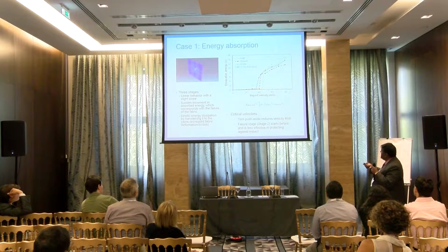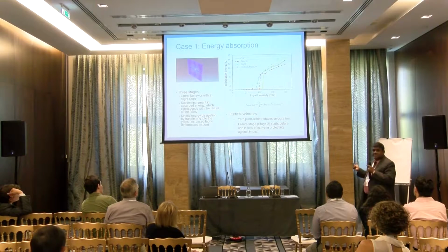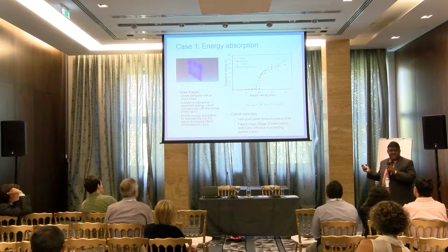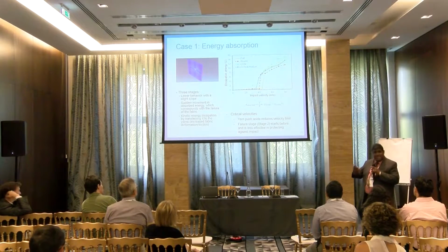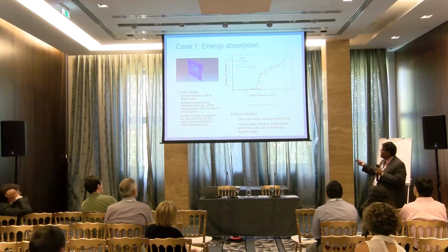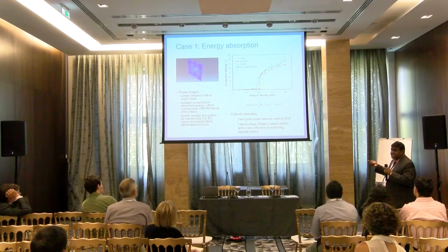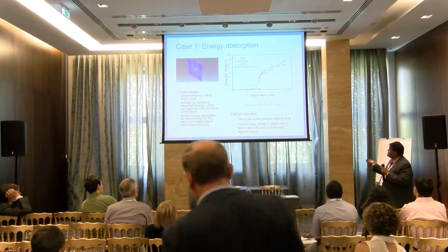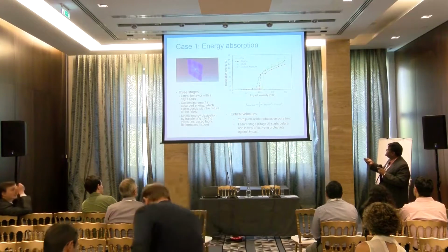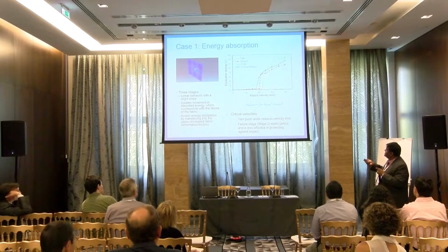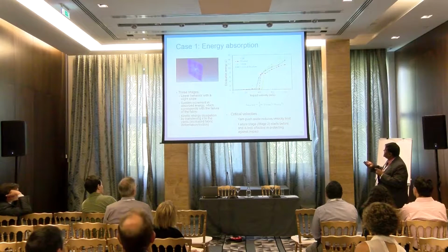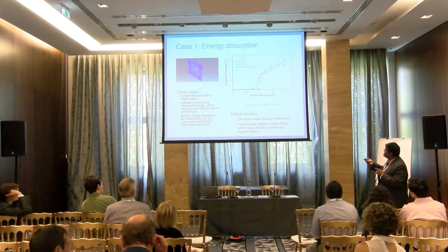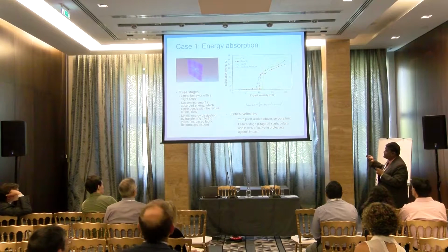So this is mainly our concern if we are concerned about V limit, or limiting velocity. The projectile should not penetrate the fabric. So this is our main zone of interest, and we can see the sharpness or the geometry of the projectile affects the initial damage and subsequently the penetration zone. So you can see if you have a very sharp projectile like a conical frustum, it quite quickly damages the fabric, and then the projectile penetrates completely.